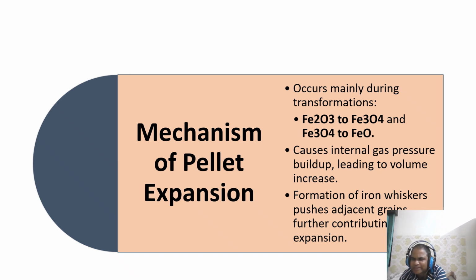Now, the most important thing is the mechanism of pellet expansion that needs to be understood from the content of the slide. Here is where things get wild. Pellet expansion kicks off when iron oxide like Fe2O3 transforms into Fe3O4 and FeO. These changes create internal gas pressure. And a lot of volume expansion also occurs, making the pellet swell like a balloon. Plus, iron whiskers form, pushing grains apart and amplifying the expansion. This is how the expansion gets magnified, and it's like a mini explosion inside the pellet.